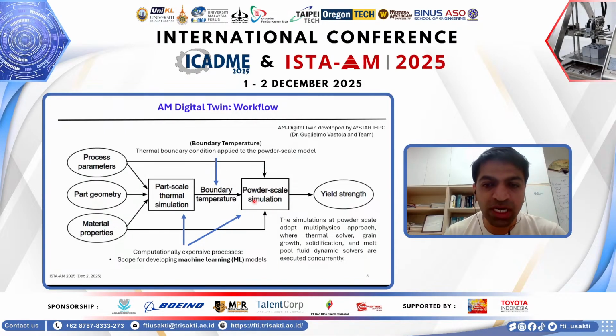So all of these multi-scale, multi-physics problems are built in the digital twin here, where the boundary temperature is an input to the powder simulations, and from the powder scale simulation results you get a microstructure of the 3D printed product, and from the microstructure we can then use homogenization methods to estimate the yield strength of the 3D printed device. That's basically our end goal.